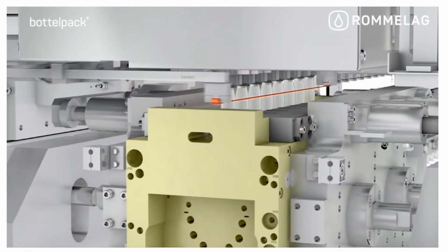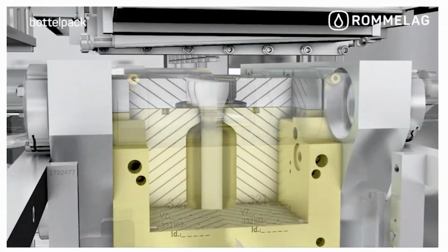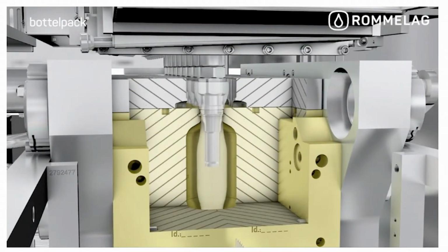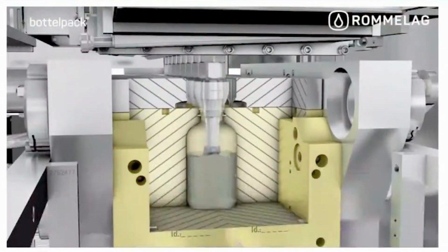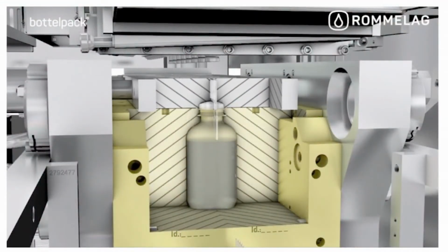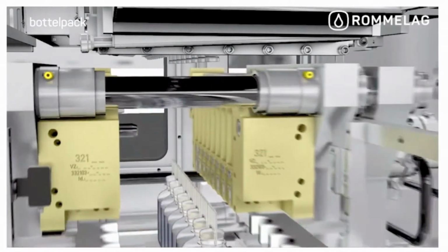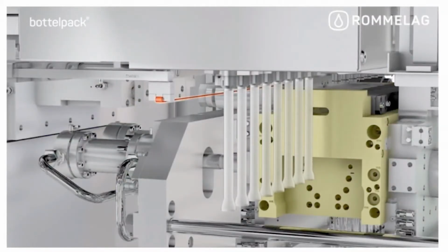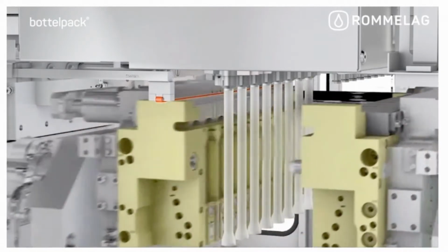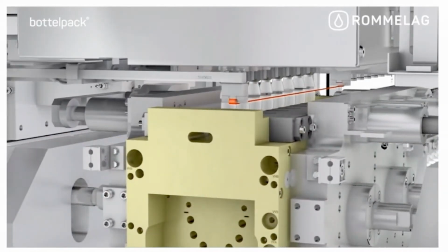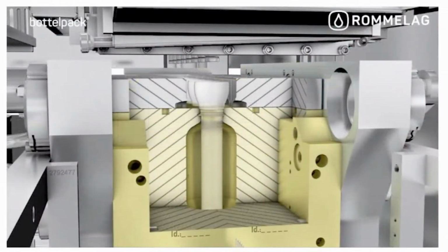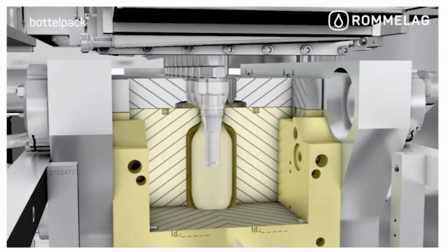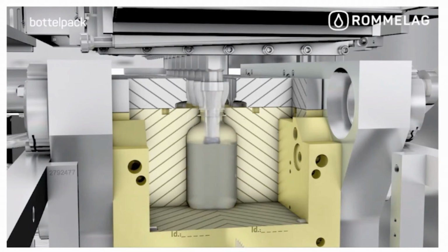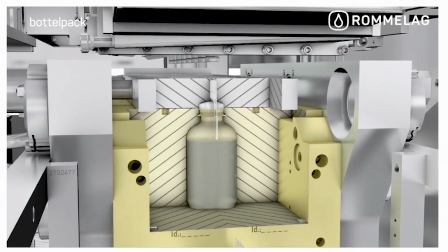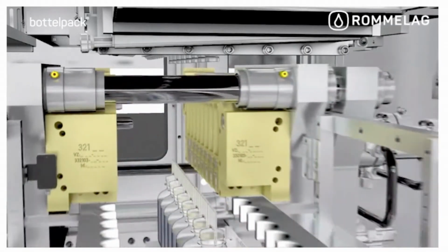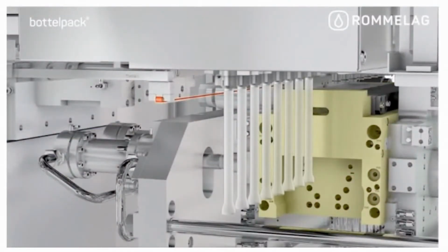The mold takes the parisons into the filling and blowing position, blowing up with sterile air, filling with the formulation, the head mold closes, and you have the final primary container. Again, extrusion, cutting with that hot knife, transferred to the blowing filling station, the blowing nozzle blows up, filling takes place, and the container is tightly closed by the sealing due to the head mold closure.